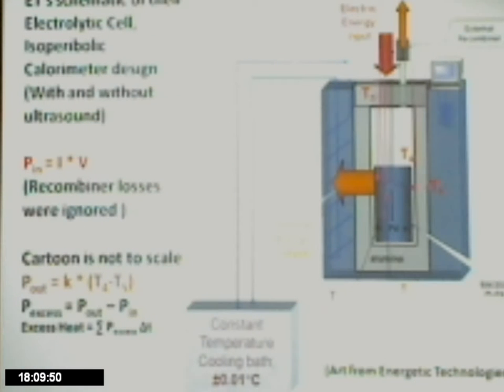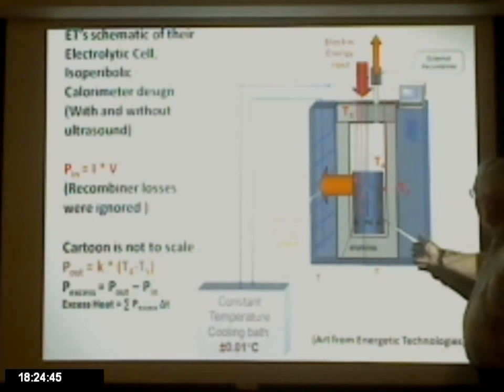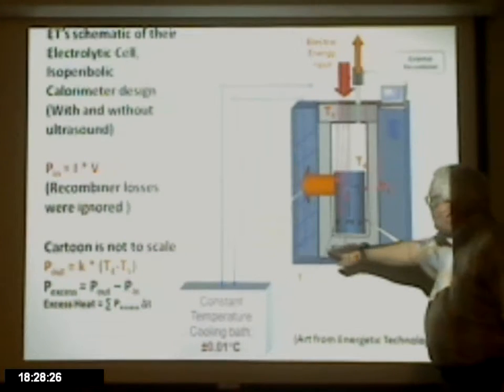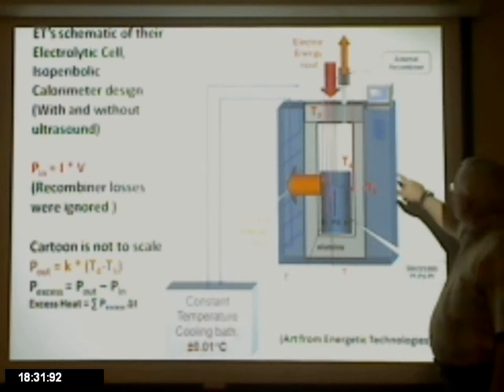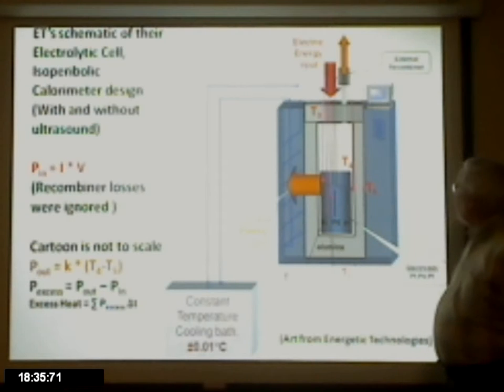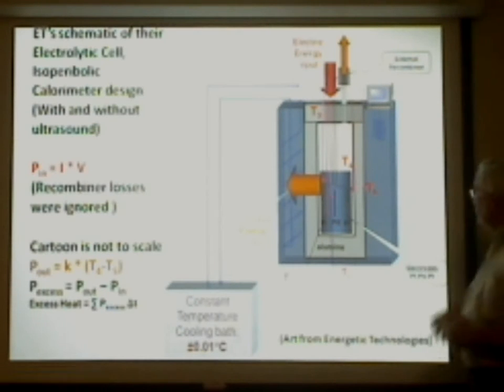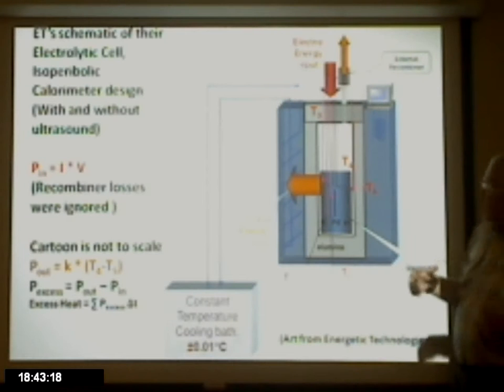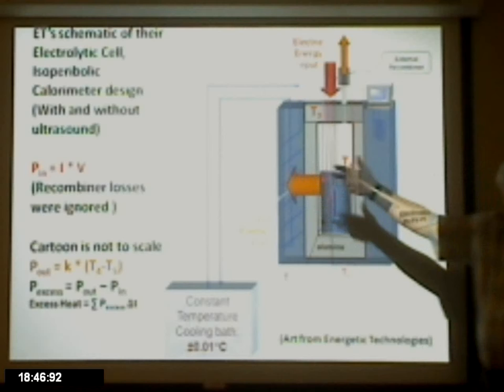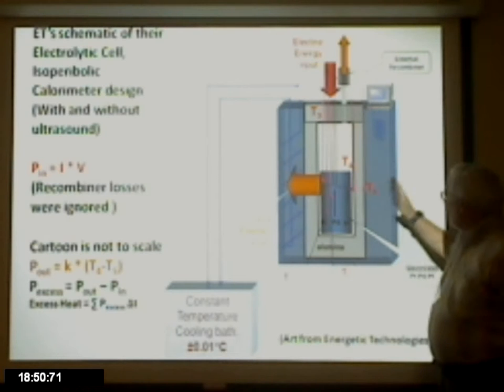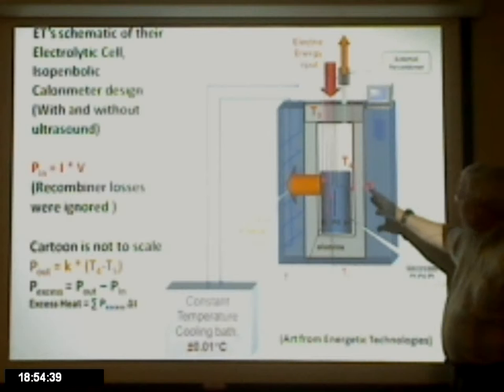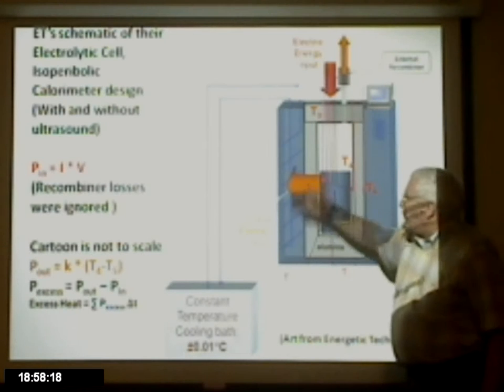First, though, I thought it would be good to talk about the 3 basic experiments they were doing, in 2 basic categories. One was this concept of an isoperibolic calorimeter. All that really means is you have a near isothermal region separated by a high thermal insulator, a thermal resistor. So you're measuring T4 being substantially above T5, and the difference, T4 minus T5, divided by some effective resistivity, is equal to the total heat flux, shown in orange, going outside of the calorimeter. Even though there will be heat capacities and it takes some time to come to steady state, you let it come to steady state, and once in steady state, you use this to infer the amount of heat out. So the output power will be proportional to this difference in temperature.